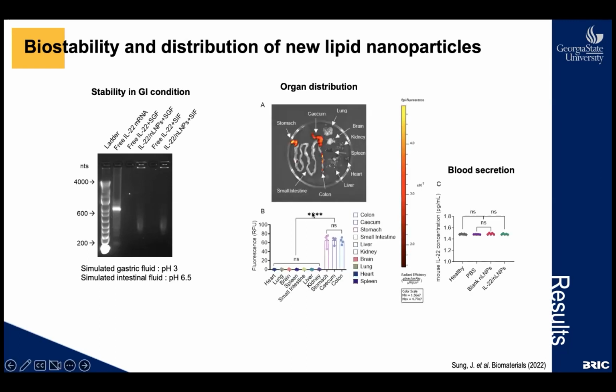On the right side, the organ distribution is important because we don't want the lipid nanoparticles to go into unwanted regions in the system, which will increase the chance of abnormal immune responses and toxicity. To prove that, we gavaged IL-22 lipid nanoparticle to mice for 7 days straight and acquired the image of distribution by measuring the fluorescence. This image shows that the lipid nanoparticle was only detected in the digestive tract, like the stomach, cecum, and the colon.